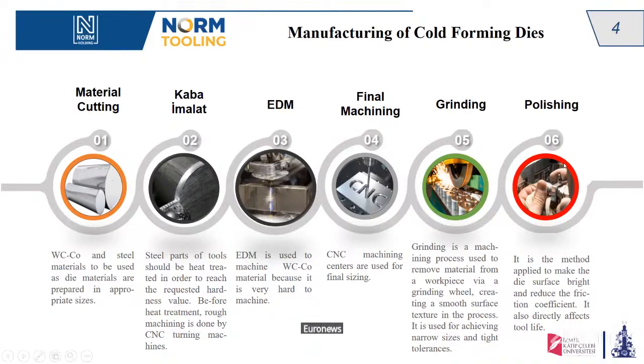The third stage is electrical discharge machining. After steel and tungsten carbide are combined, the tungsten carbide material is primarily machined using the EDM method due to its difficulty in conventional machining. The fourth stage is final machining. CNC machining centers ensure that the dies are brought to the desired dimensions specified in the technical drawings. The fifth stage is grinding. Grinding is a process used to remove material from a workpiece with a grinding wheel, creating a smooth surface texture. In cold forming dies, this is a manufacturing method used for parts requiring contact with the workpiece due to very narrow tolerances. The sixth and final stage is polishing.